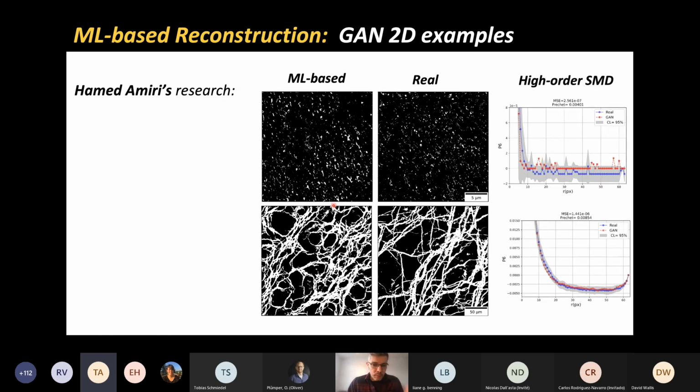Now, after we do the machine learning, we can take some of our high order metrics, in this case those polytopes that I told you about, and ask the question: has the machine learning reconstructed samples that maintain the high order statistics of the original samples? What these pictures show you is that that is true. For the top, in this case a hexagonal polytope, you can see that it becomes random very quickly.